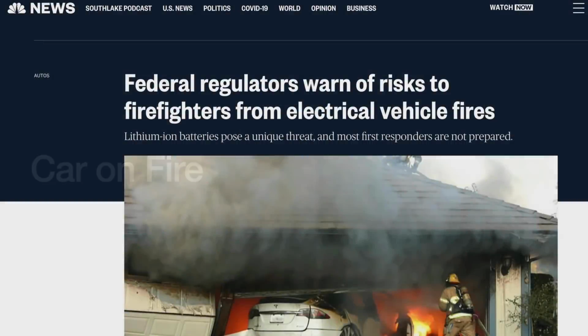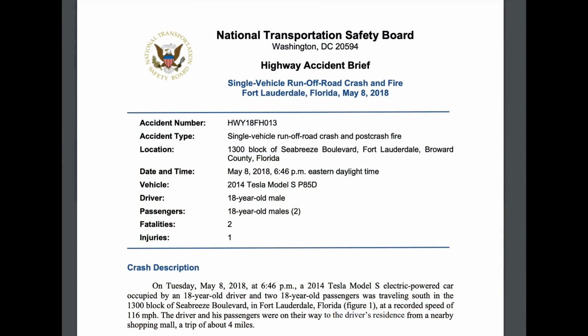EV fires are not your regular garden variety car fires, if such a thing exists. Because they are partially caused by direct reactions between battery components, they may not require external oxygen. Therefore, firefighters generally find them more difficult to extinguish than conventional vehicle fires. One example in the city of Fort Lauderdale in the United States took between 750 to 1,100 liters of water. In some cases, it can take over 10,000 liters of water and over 60 minutes to suppress an EV fire. This is substantially more than the 5 minutes for a conventional car fire.